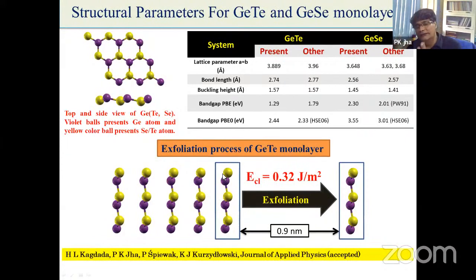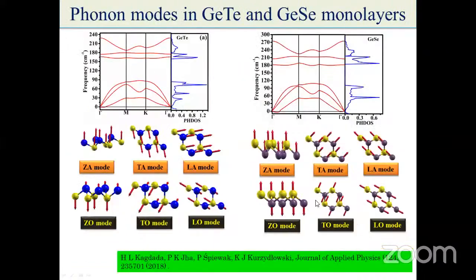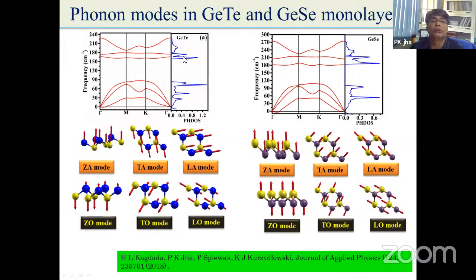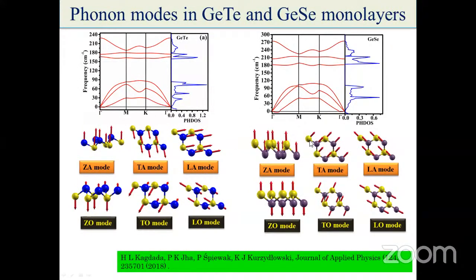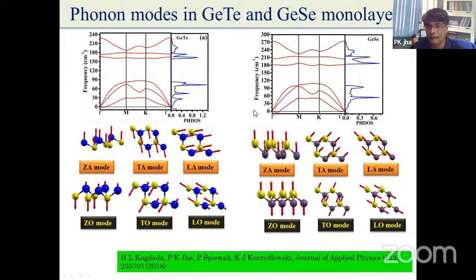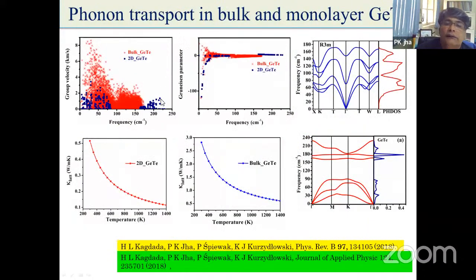One can make the germanium telluride and germanium selenide monolayers, by the exfoliation process of GeTe. This is the cleavage energy, so we can have the single layer of that with this much separation. And you can see here the phonon dispersion curve for both GeTe and GeSe with a very minor imaginary phonon modes, right? You can see that the nature of the phonon dispersion curve is more or less the same, except the values of frequencies. In the lower part, we show the eigenvector, right?